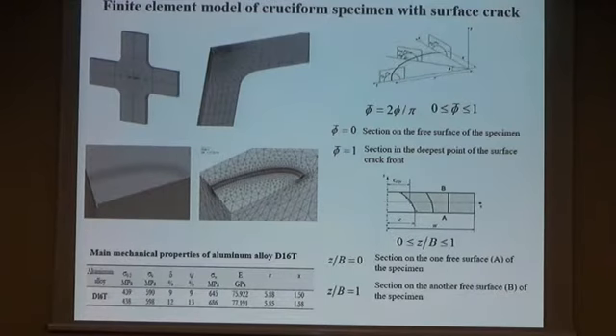Finite element analysis will be performed for both surface cracks and through thickness cracks. So you can see the typical finite element models for cruciform specimens. And for representation of our results, we used dimensionless coordinates. In case of surface crack, we used a dimensionless angle phi. And in case of through thickness crack, we use a dimensionless coordinate Z normalized by thickness of the specimen.